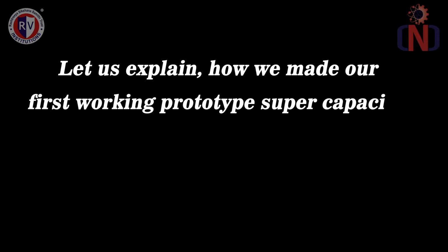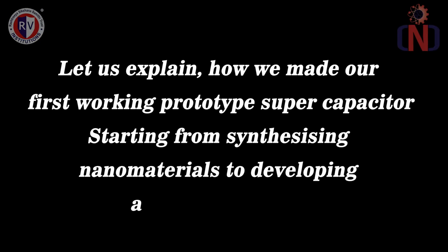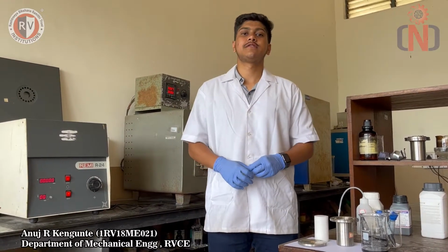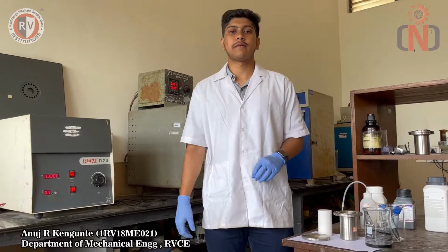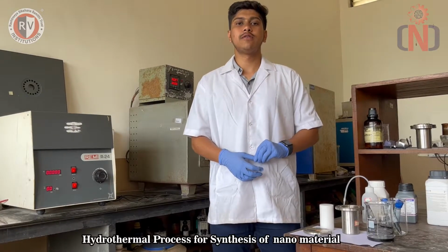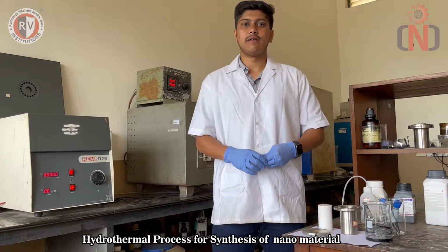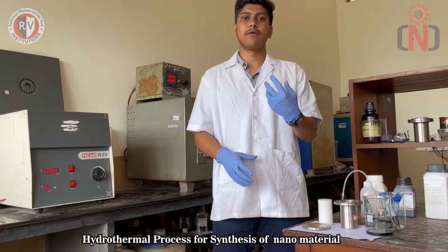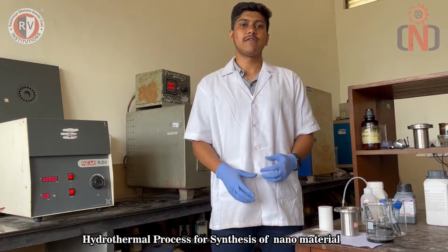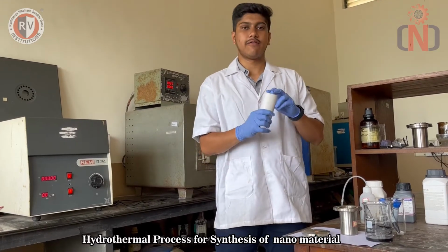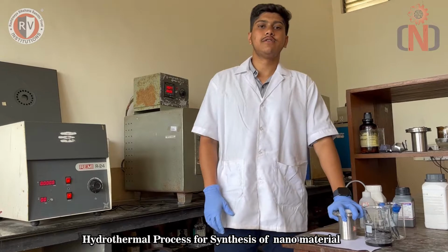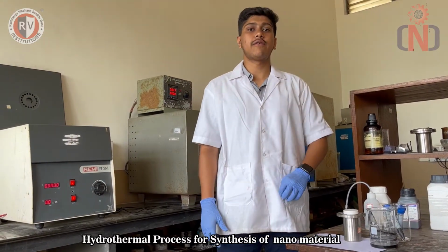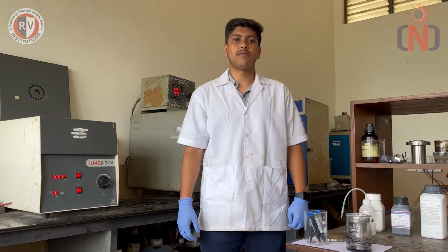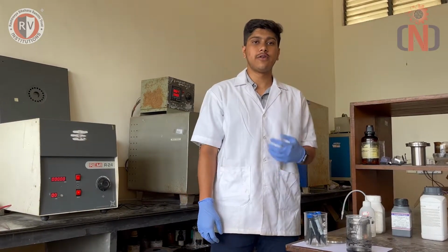So let us explain how we made our first working prototype supercapacitor, starting from synthesizing nanomaterials to developing a prototype device. We have synthesized transition metal chalcogenide based nanomaterials for our supercapacitor applications. The stoichiometric amounts of transition metal salts are dissolved in the required amount of distilled water along with the chalcogenide source, kept in Teflon tubes which are placed in the autoclave, and given hydrothermal treatment at 180 degrees Celsius for 2 hours. After the hydrothermal process, we have kept our product for cooling until room temperature.